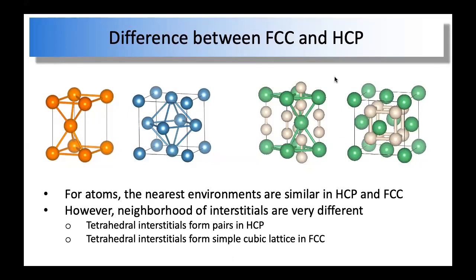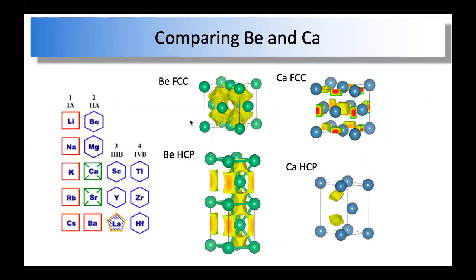So you can imagine that if you have electron localization here, then the localized electrons at these quasi-atom orbitals will strongly interact. And that's exactly what happens for beryllium and magnesium. If you take beryllium, remember that this localization changes with the lattice, but because of the particular local lattice of beryllium, the electron is mostly localized at the tetrahedral site. They do have small occupation values at the octahedral site. It's also a maximum, but that value is much smaller than the occupation of the tetrahedral site.